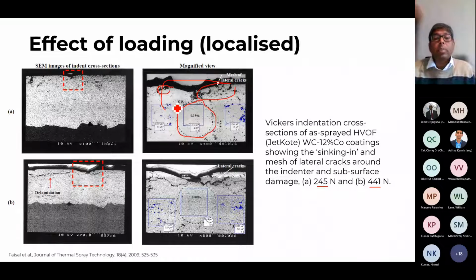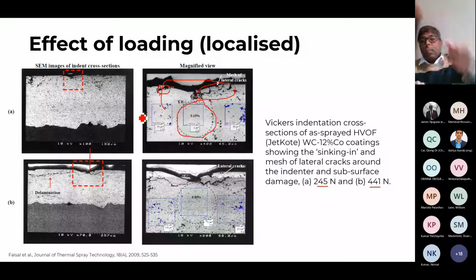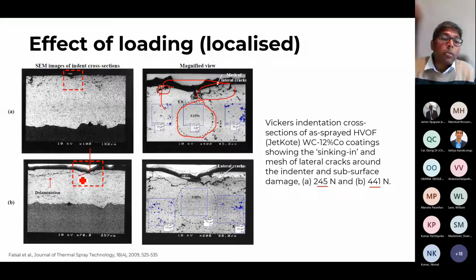You can see huge material cracking has happened, normally at the edge, and the densification happened because these coatings are porous. Now, when you remove the load, when you remove the indentation, there will be relaxation in the stress. So when you remove it, the relaxation can induce lateral cracks, and you can see all these cracks. So actually the indentation was very localized. The size was about 50 micron, but this went on for a very long length.